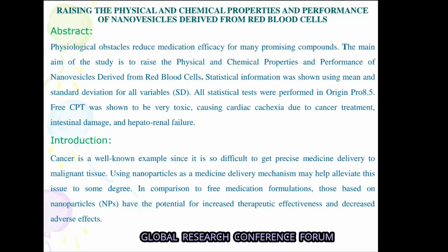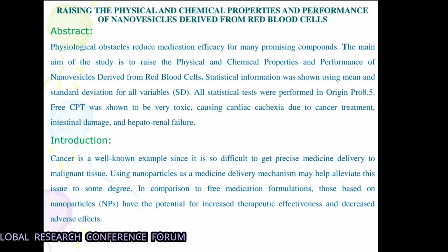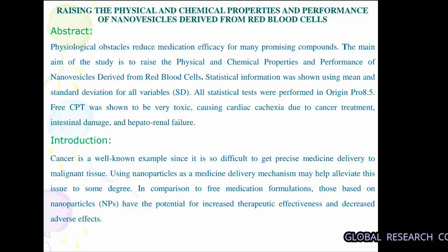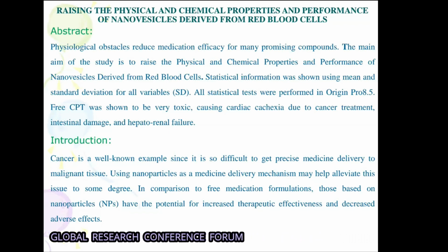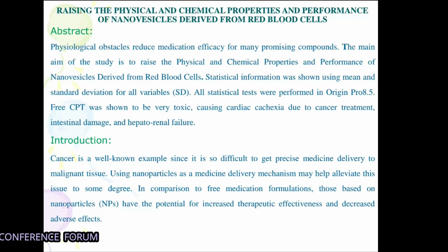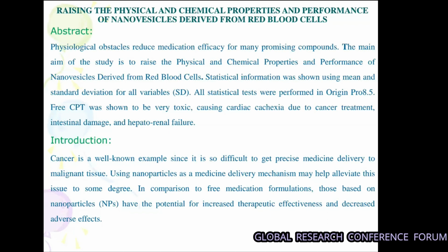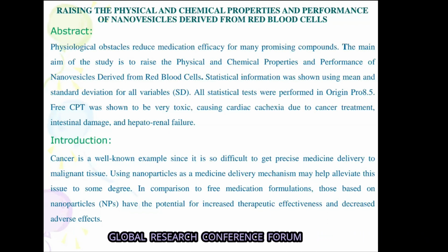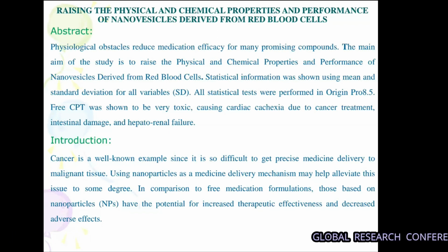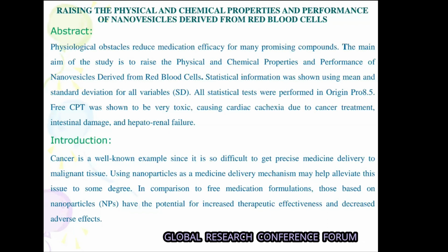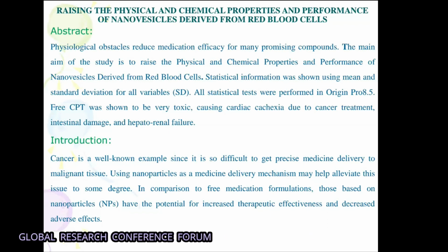1. The encapsulation efficiency was determined using centrifugation. To do this, we measured the CPT concentration of suspended micelles and used centrifugation at 1000 g to selectively precipitate the unencapsulated medication. At a 1 to 1 PEG-PCL to CPT ratio, we only managed to encapsulate 15% of the drug, as we can see in the figure.